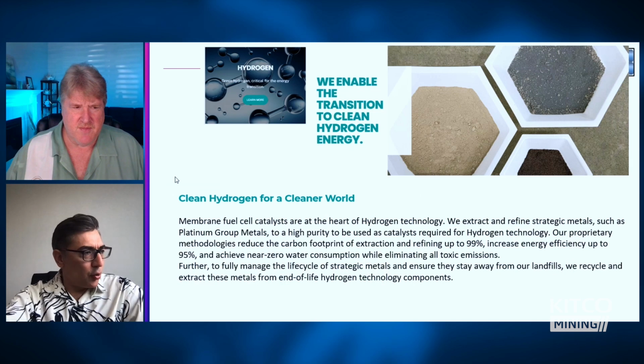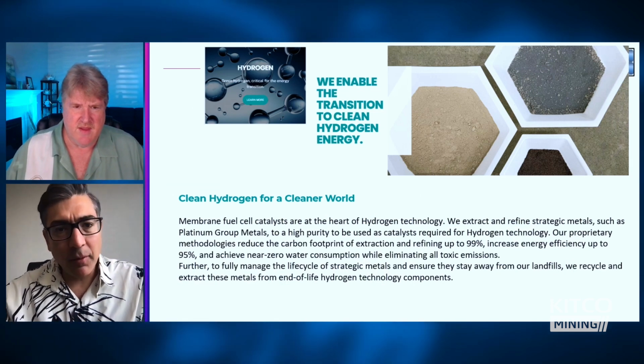Yeah, we have actually two impacts in hydrogen economy. Number one is, as exactly you mentioned, we can extract these metals from end-of-life stacks, from end-of-life membranes, electrodes. Then we can extract platinum, iridium, ruthenium, and have it back into the circular economy. And the other one is actually we produce hydrogen because we are using electrochemistry, and our electrochemical reactions are through an electrolyzer that has been developed in-house. And we produce hydrogen that can be captured. For our PGM process, the hydrogen is not significant because our electrolyzers are small, and the hydrogen amount is not significant to capture it and use it in a meaningful way.